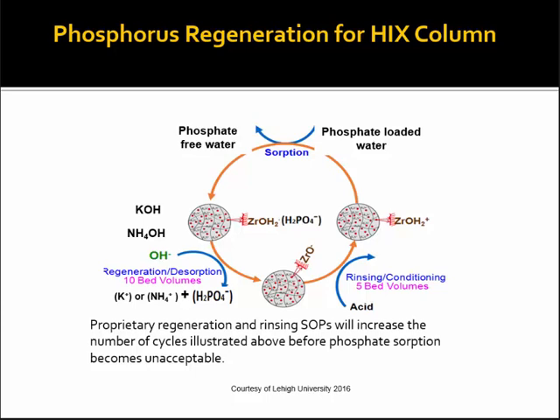All the sites get saturated. You add your alkaline, so I'm proposing a combination of potassium and ammonium, and you end up with ammonium phosphate solution. You give it an acid rinse to get your pH back to neutral and clean up the resin, and now you take it back out to the field to do more capture.